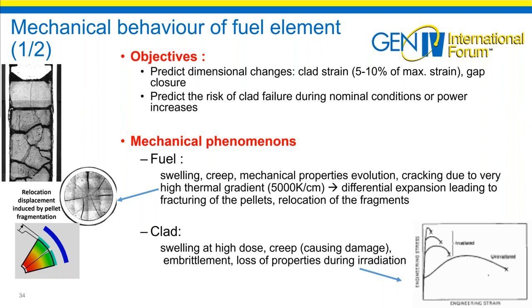The mechanical phenomena to learn for the fuel are first the swelling, the creep, the mechanical properties, and the cracking due to the very high thermal gradient with differential thermal expansion. We also have to take into account the relocation of the fragments that can enhance the heat transfer. For the clad, it will be taken into account the swelling at high dose, the creep, the embrittlement, and the evolution of the properties during irradiation, like the elastic limit, as we can see on the figure, and it's lower after the irradiation than on the fresh fuel.